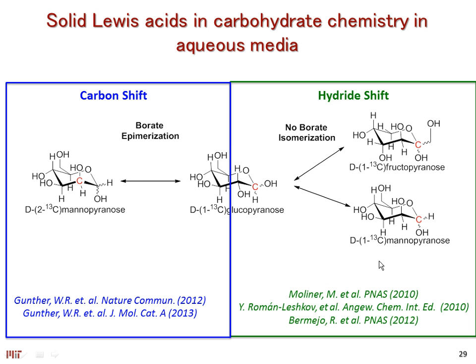Some of the work that we did at Caltech, working with sugars, was to exploit this feature of Lewis acids to shuttle hydrides intramolecularly within the same molecule. You can see that, for example, glucose can undergo an intramolecular hydride shift and isomerize into fructose this way, rather than doing classic proton abstraction chemistry as you would with a base catalyst. Something we have found as well, which is very interesting, and I will not talk too much about it today, is that in the presence of borate salts you can change how this sugar is complexed to the active site, and instead of a hydride shift you can have carbon shifts. You actually break carbon-carbon bonds within the sugar and rearrange them.